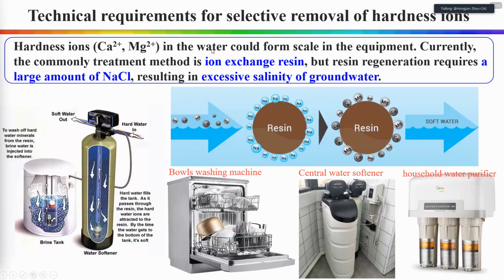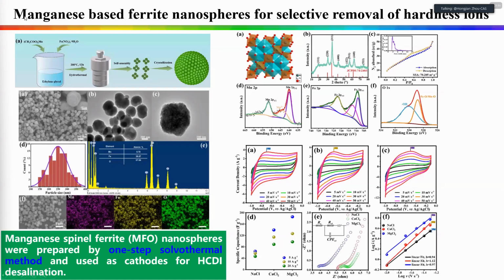This is our first part. In the second part, we try to use CDI technology for the selective removal of hardness ions. As we know, hardness ions in water can form scale in equipment. Currently, the common treatment method is the ion exchange resin, but resin regeneration requires a large amount of sodium chloride, resulting in excessive salinity of groundwater. Now, America and Europe are trying to prohibit this technology for hardness water treatment. But our CDI has this advantage. So we tried to find out what material can do this. In the end, we found manganese ferrite, which has good selective removal of hardness ions. We used a one-step solvothermal method to develop our material.